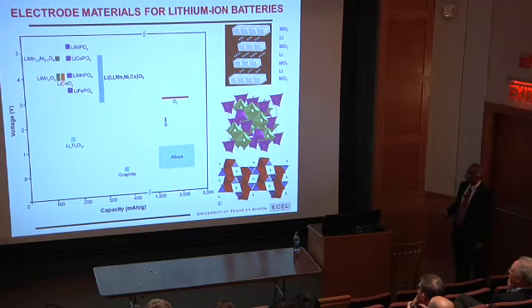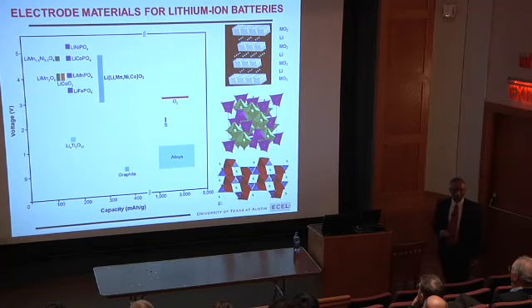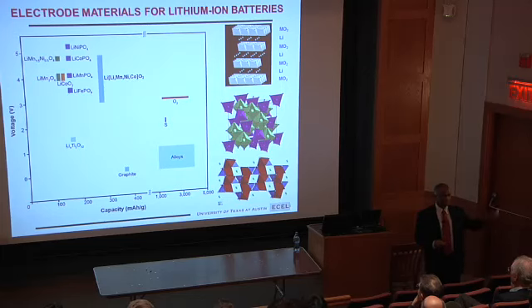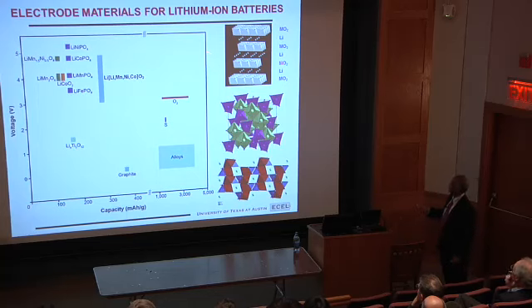And then in laptops and cell phones, you use a material, lithium cobalt oxide, or solid solutions containing cobalt, manganese, nickel instead of just cobalt alone. That has this layered structure, two-dimensional. That is basically the sodium chloride structure if you love material science. But the charge difference between Li+ and Co3+ is large, and also they have a large size difference. Therefore, the Co3+ and the Li+ tend to order along alternate (111) planes of the sodium chloride structure, so it becomes a layered structure.